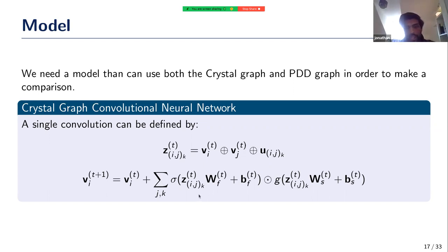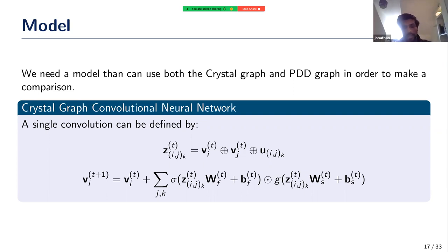Because the cutoff radius is redundant in CGCNN, we use a high enough cutoff radius for all crystal graph examples such that each node has at least k neighbors. The authors also note that pruning edges with too high a cutoff radius actually lowers performance, so to get the best possible result from the crystal graph for comparison, we use a high enough cutoff radius that no edges are removed.